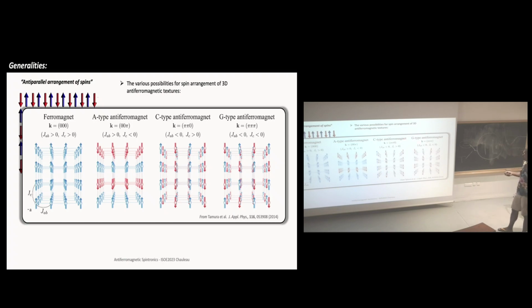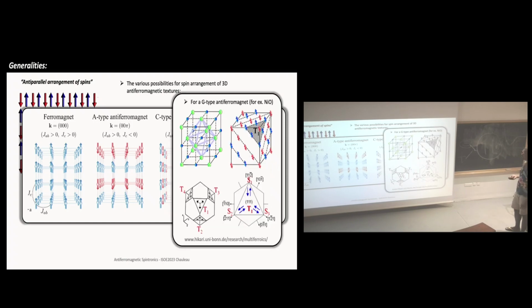And you have the very well-known G-type antiferromagnet, because in this case, all the neighboring spins are antiparallelly aligned. So we are very often dealing with this one. So already it makes quite a more complex, quite a richer spin configuration compared to the ferromagnet. But on top of this, you have to consider that actually you can have magnetic domains, and you have different ways of arranging those spins.